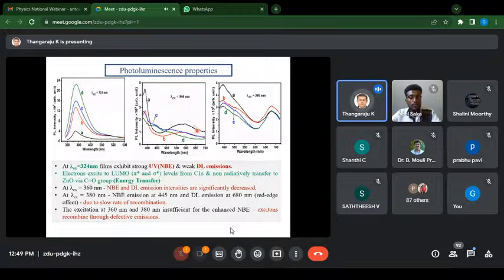And you can see that the hybrid material excited at different excitation wavelengths will not show any emission from the doped or incorporated AlQ3 molecules, which confirms that the energy of the adsorbed AlQ3 molecule is transferred to the zinc oxide. So this property is being used in the photo detector applications.